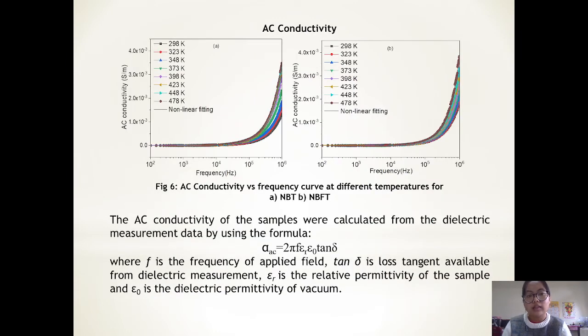The AC conductivity was also calculated from dielectric measurement, and we can see that the AC conductivity increased with temperature, which shows the negative temperature coefficient of resistance, which also shows the semiconducting behavior of the samples.